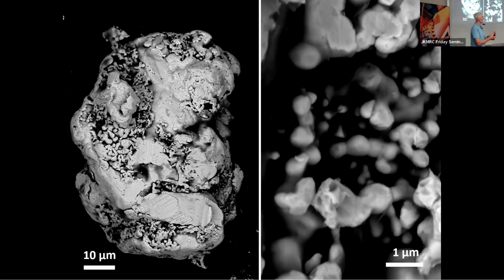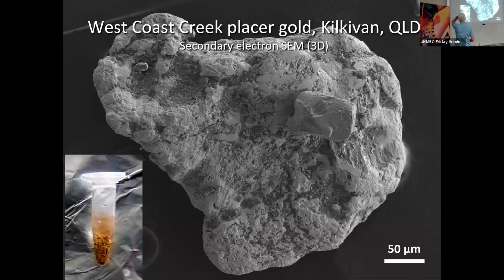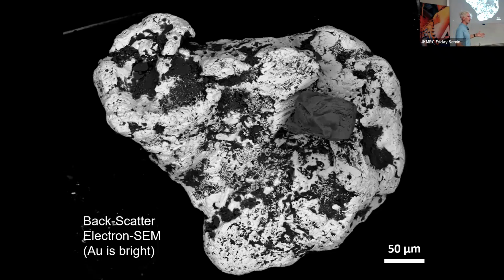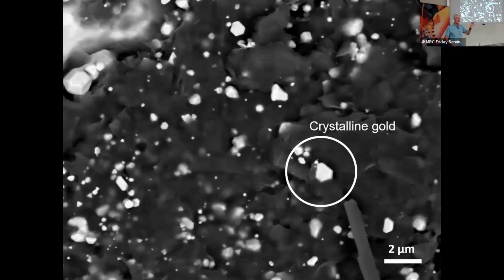Well, gold's cool, but you know, it's inert, it doesn't corrode. Yet, when you look at gold grains, and so here's some gold from Kilkivan, panned out, secondary electron image, so we've got kind of 3D, you can get all the scrapes and knocks and things that happen to gold grains. Gold is very soft, and you can imagine if you're dragging it down a stream bed, you think it should be weathering and breaking down. So if you weather gold, how can you then grow gold grains? It's opposite. If we look at this sample here with backscatter electron, so high atomic mass is bright, low atomic mass is dark, we've got within this nooks and crannies and these ideas of corrosion pits, so gold dissolving. But if we zoom into these dark horizons here, we also see gold precipitating.